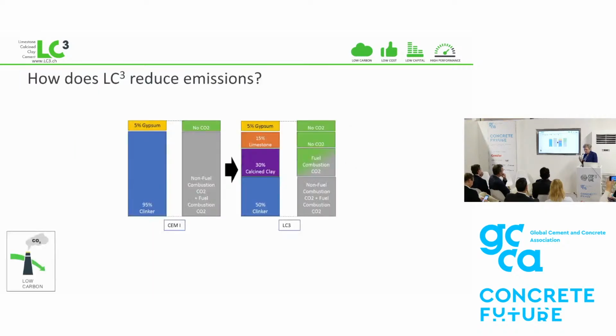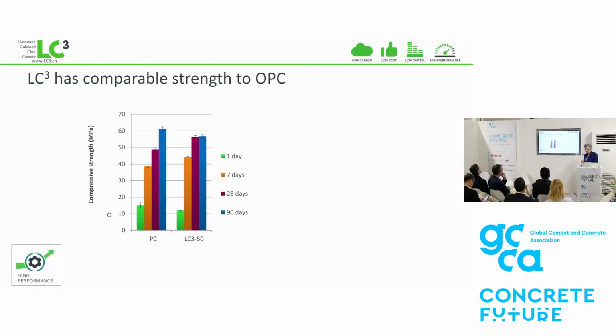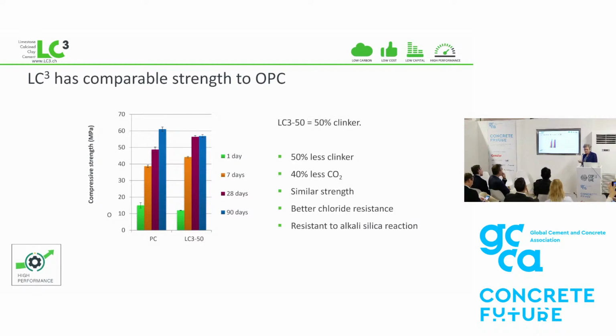So it's fairly straightforward why LC3 reduces CO2. We substitute the CO2-emitting clinker with a combination of calcined clay and limestone. Now, limestone has virtually zero emissions. Calcined clay, you do have to calcine it, but the heat you need there is much, much less. So you still gain a lot. In a nutshell, you have 50% clinker substitution. You will save 40% CO2. And as we see here, you will get similar strength to Portland cement in as little as 7 days.